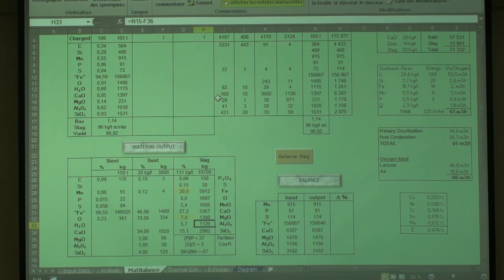So that's why I consider Al2O3, I mean aluminum, only as oxide for the scrap. So then CaO is calculated based on the target basicity. So I just consider the silicon times the basicity, and this is the amount of CaO I will have in the slag. Alright?